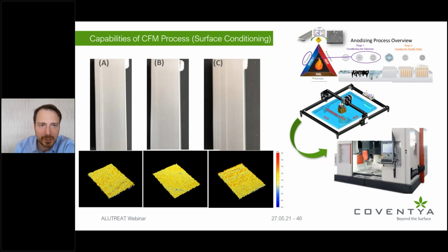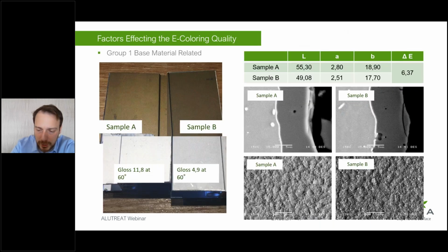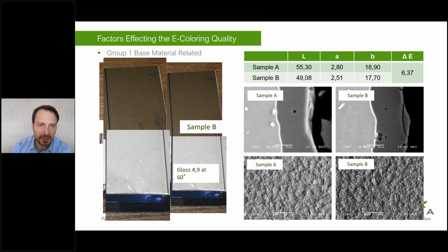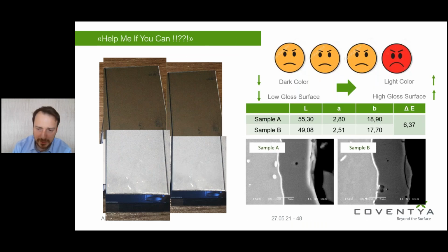Therefore, as we have previously suggested, it is much more flexible when you have a process like the caustic-free mat we have introduced, where you can adjust the surface gloss and also adjust the alloying elements distribution on the surface. Therefore, by using this approach and evening out the surface and making it exactly the same by removing some of the unwanted intermetallics, by removing the grain boundaries, and then finally by etching the right amount, you can basically get exactly the same color, making our very unhappy team a little bit more happy, because you see that we still have 2 more steps to go related to anodizing and then related to coloring chemistry, which hopefully at the end of the day, I see that Ms. Pinar will be smiling again.